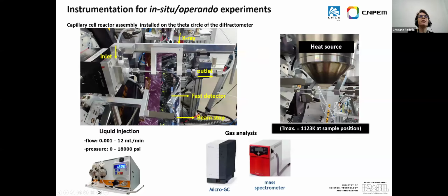The X-ray comes in this direction, and we have a beam stopper installed here so that the direct beam doesn't touch the detector. As I told you, we can work with liquid phase, and for this, instead of flowing gas, we have this liquid injection. And here I'm showing our heat source that goes very close to the sample to increase the temperature during the measurement.